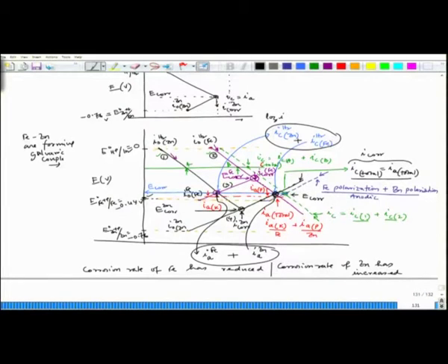So, now interestingly, one more information: before coupling, the IC of hydrogen evolution reaction on zinc surface was at this point, and after coupling I could see that hydrogen evolution reaction rate or IC on zinc surface has gone to this point.